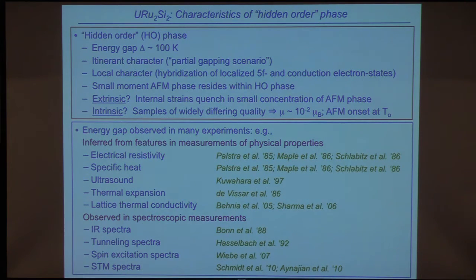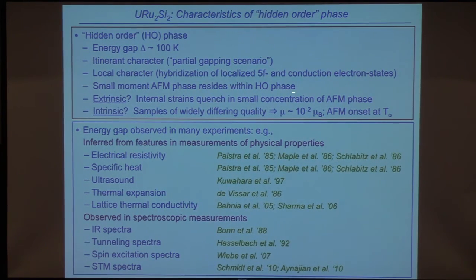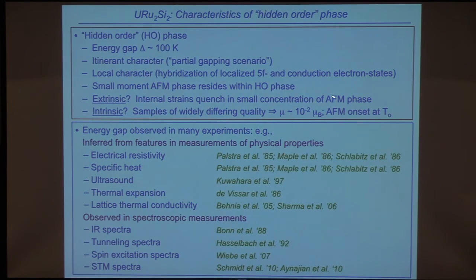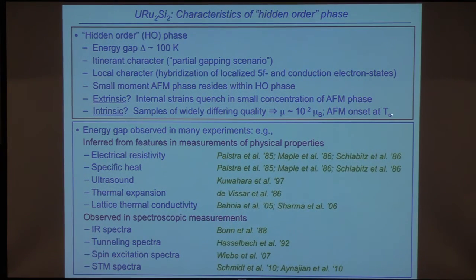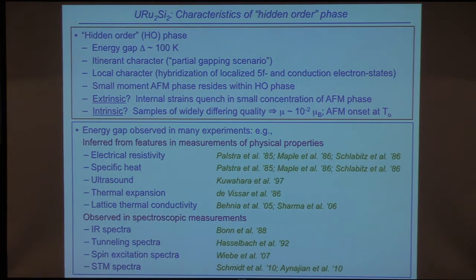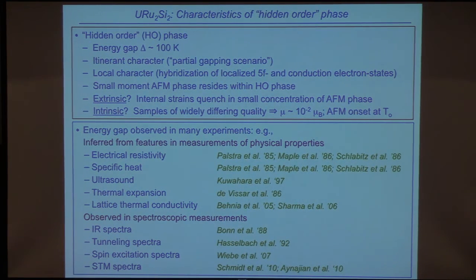Now, to be fair, there are some people who believe it's intrinsic, and evidence for that is that samples of widely varying quality, at least measured by neutron diffraction, always give you a moment of a few hundredths of a Bohr magneton, and the antiferromagnetism onset is at T0. Okay? But I think most people think it's extrinsic. So the energy gap has been observed in many experiments. All of these old experiments indicated here. Also in infrared spectra, tunneling spectra, spin excitation spectra, STM studies. And so the energy gap certainly is one feature of this phenomenon that is solid.